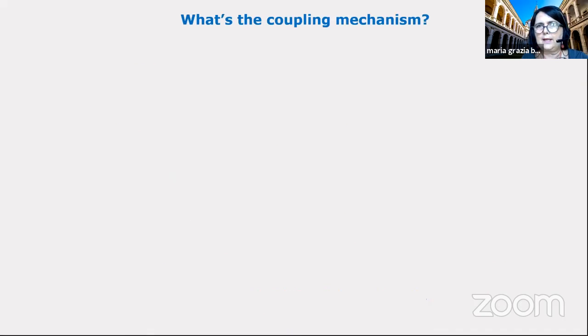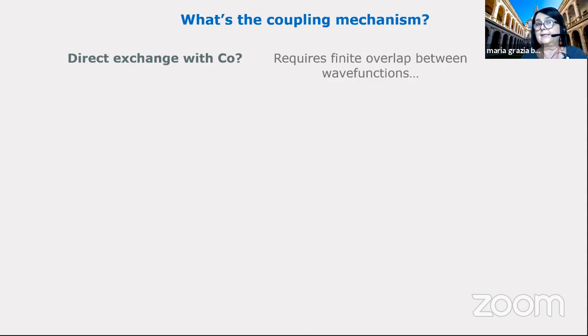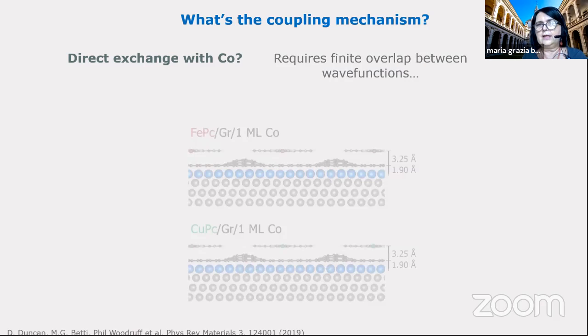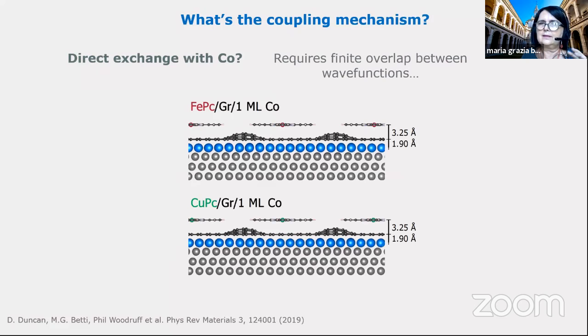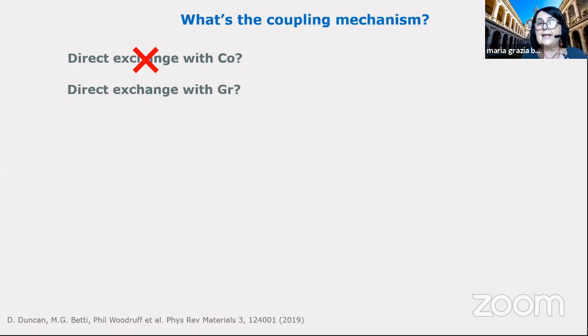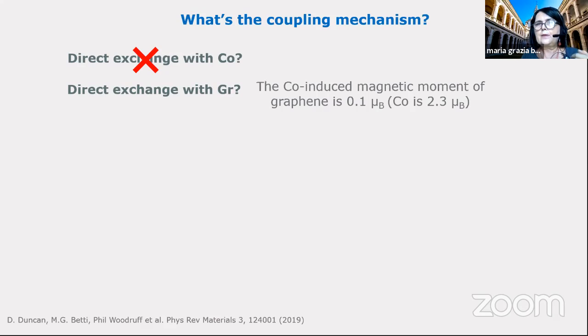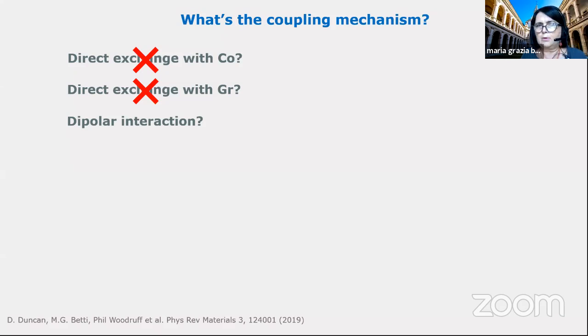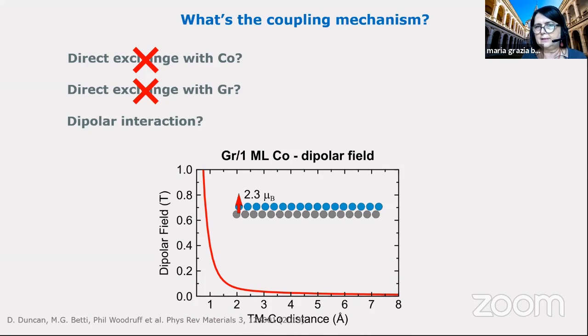But if you want to understand why, we can try to see if there are different reasons. You can have a coupling because of direct exchange with cobalt. In this case, you require an overlap between wave functions. Here the distance is very large. They are more than 5 angstrom apart. So in these 2 configurations, which are calculated, but we also made an experiment, X-ray standing wave, it's not possible to have an overlap between these wave functions. Then we can have an exchange mediated by graphene, but this is also not possible because the calculation says that the magnetic moment associated with graphene is very, very low. Then another possibility is dipolar interaction, and even in this case, if we calculate this dipolar interaction, it's not possible.